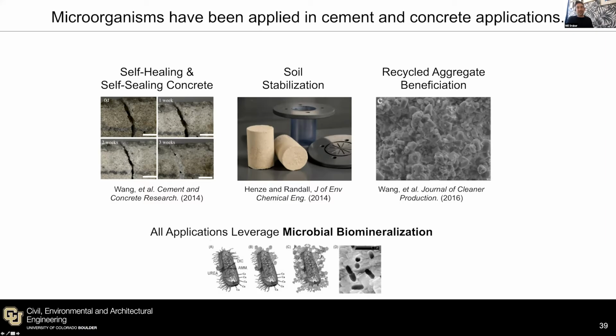There's an issue with this because concrete's a very aggressive environment, like I already said beforehand, and the microbes don't always survive at levels that we would need them to survive if we want them to be viable for decades. But again, this concept of using microbes that biomineralize has been applied to the self-healing concrete field. It's also been applied to stabilize soils, and it's also been applied to densify recycled aggregates. So if we bust up old concrete and we want to use it as the rocks in new concrete, some researchers had looked at using microbes to help biomineralize and densify that aggregate to improve the aggregate quality.